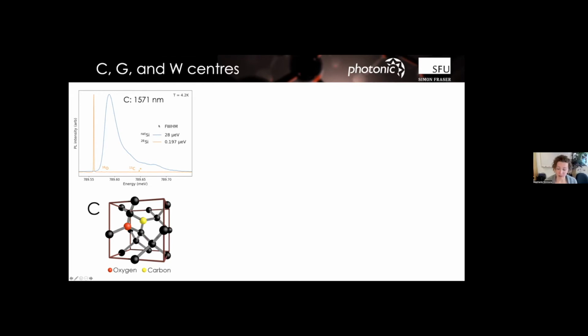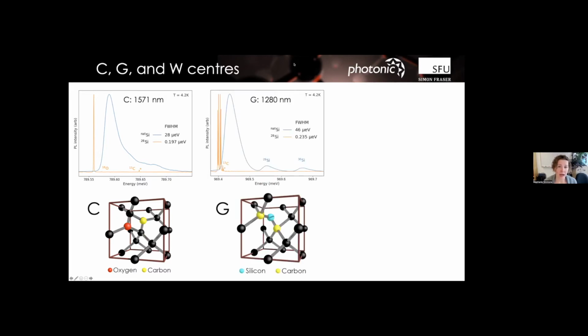So we have something right in the telecom region. The G center is almost impossible to get rid of. It's such an easy to form defect, and it's everywhere. And when we went from natural silicon and looked at it in silicon-28, we got to see all this additional structure, which again, it's not magnetic, sadly. We were really excited about that for a second, but it's not magnetic.